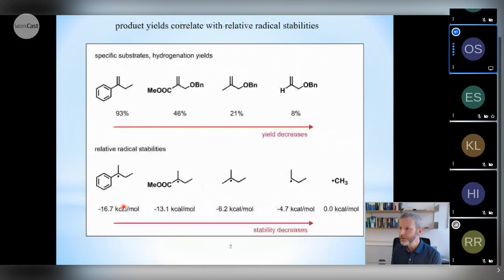And this radical intermediacy is further corroborated by this correlation of product yields, of hydrogenation yields, that correlate rather well with these relative radical stabilities. You see here the benzylic radical, as you know, is quite stable, certainly with respect to this reference point here. And this is also the substrate for which Miriam gets the best yield. And then as she goes to less stable radical intermediates, the yields tend to decrease.